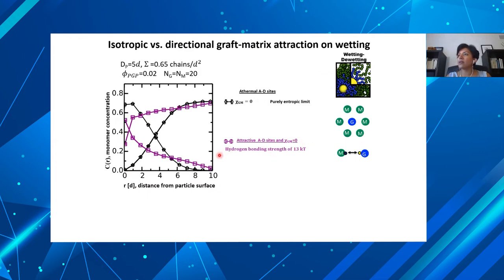Now let's look at the pink or the purple line. This is what happens when you now incorporate directional interactions between the graft and the matrix through those little sticky beads. You see that the grafted layer is now stretched out, right? It's going farther and the matrix is going further in. And so there's increased wetting. What if you did this isotropically? If we had incorporated isotropic attractions, now of course here I'm using a model chi parameter. These are basically increasing attraction strength between the graft and the matrix beads isotropically. So these values will be much smaller in kT compared to this, because this is a very small volume, very strong.